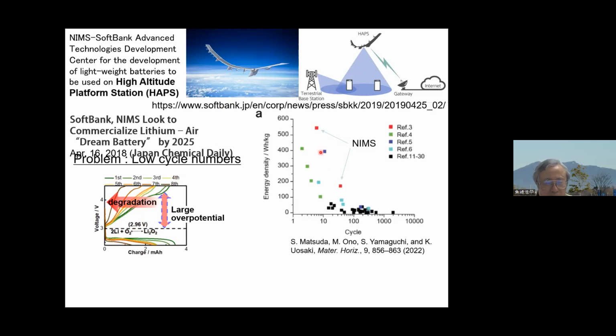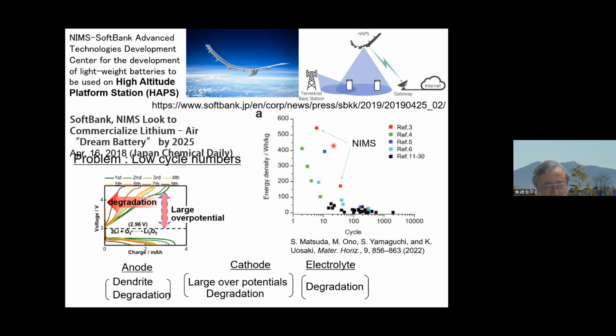And then we recently reviewed many papers published so far, and they plotted energy density as a function of cycles, or cycles as a function of energy density. So our results are one of the top, but still the number is very low. So we are required to have something like over 500 watt-hours per kilogram. But in that case, we still have only something like 10, 15 cycles. So it's very bad. So what is the problem?